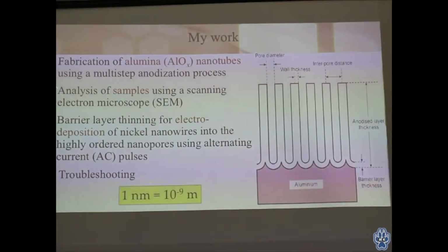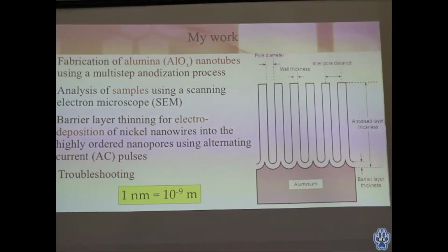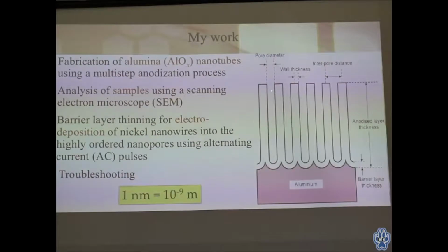After we analyzed these samples and found that we had a really highly ordered array of nanopores, we wanted to work on reducing this barrier layer here down on the bottom of this image right here. The barrier layer is really just this connection in between where the aluminum and the oxide starts growing. The reason why we want to thin the barrier layer is because we want to increase the pore diameter of these samples and reduce this layer here without actually removing the entire thing.